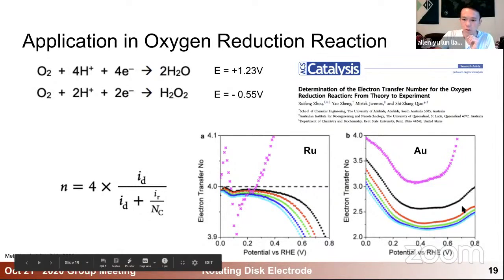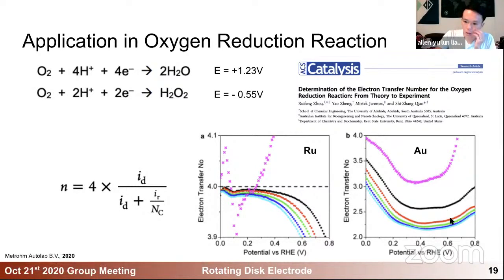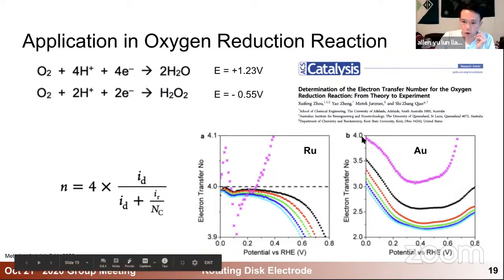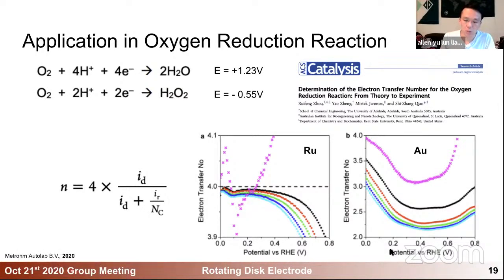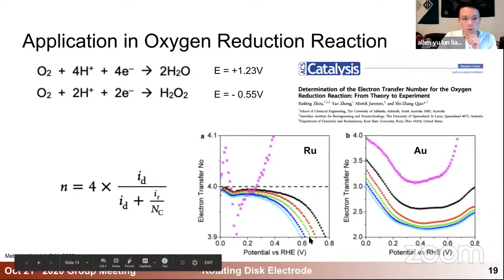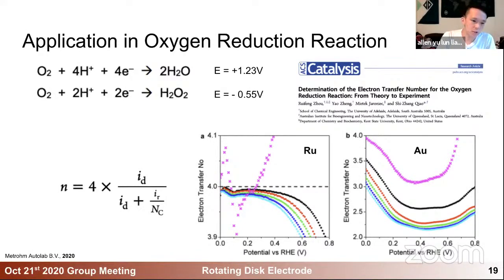the different colors mean different rotating speeds. But for gold, it can actually have a mixture between 4-electron transfer and 2-electron transfer, depending on the potential and the rotating speed you choose. So that's a way to use the RRDE and its extension to study the reaction mechanism of the oxygen reduction reaction, or it could be another reaction you are interested in.